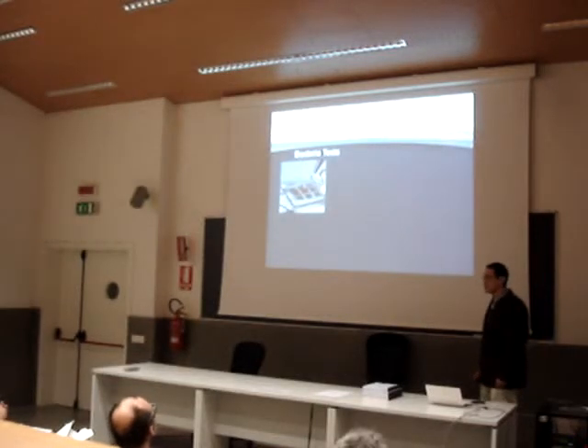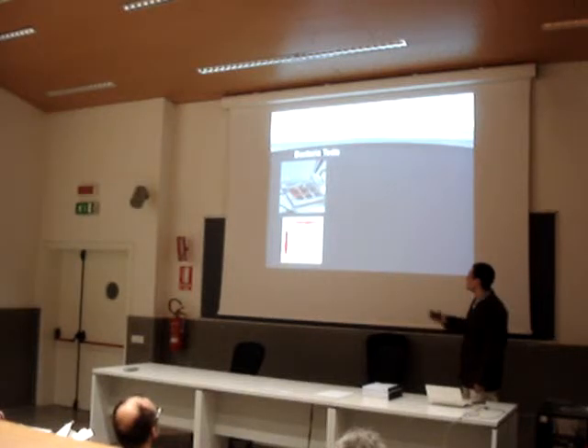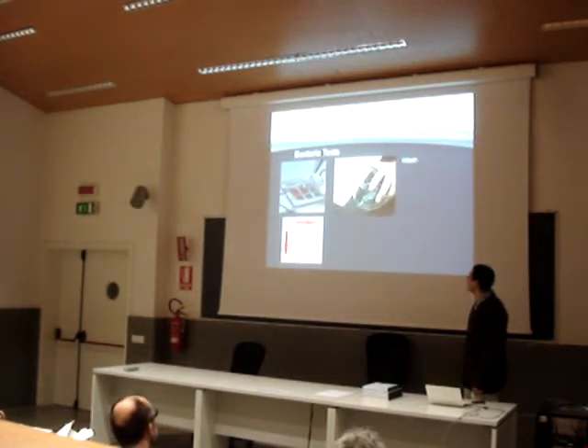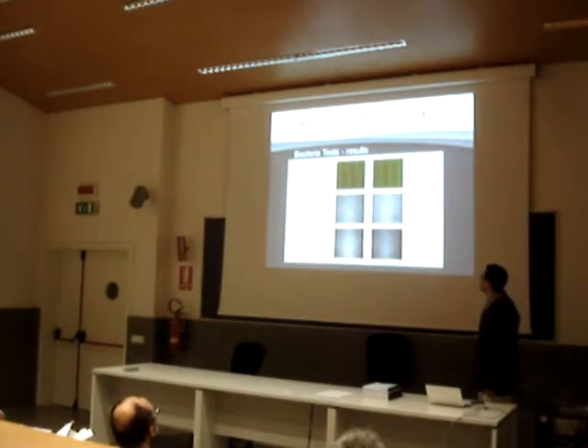So I made bacteria tests on Karolinska Institute in Stockholm. We put with measurements in different directions. We wash out the chip, and then we look at it in the microscope to see how many bacteria were attached. And the chip, at the first moment, were no bacteria attached at 30 minutes. Then I put Teflon on glass slides, and after 30 minutes, there were no bacteria attached neither. But after 24 hours, we see some bacteria attached to the glass.